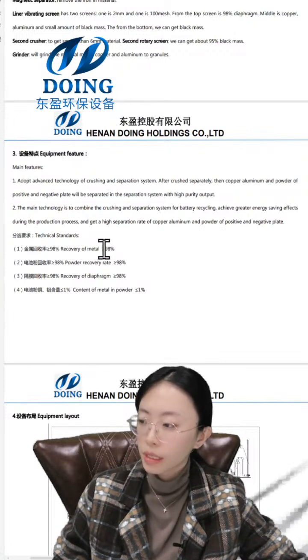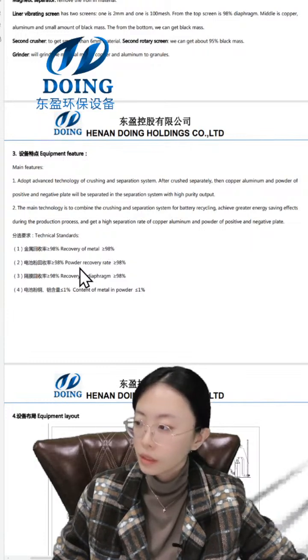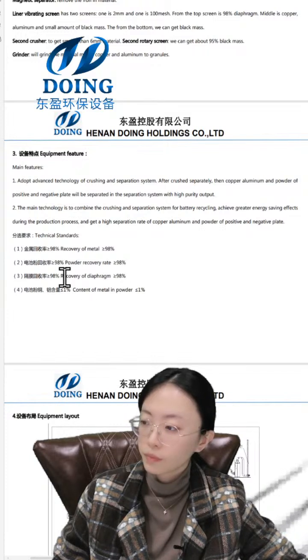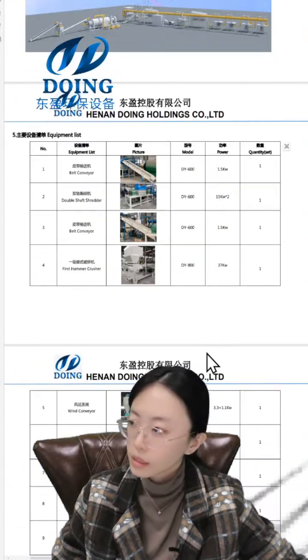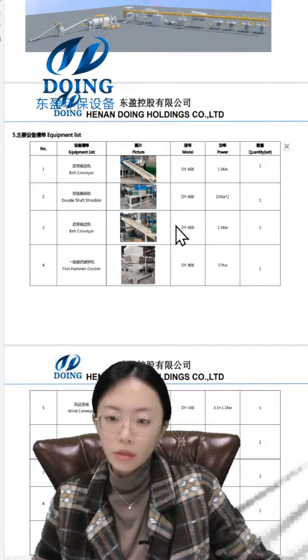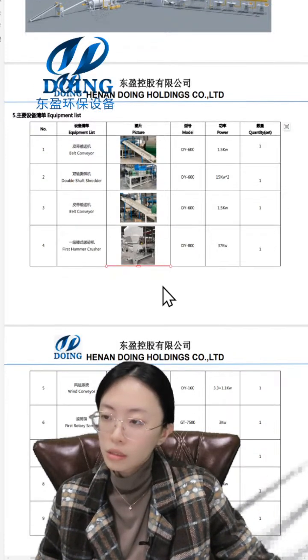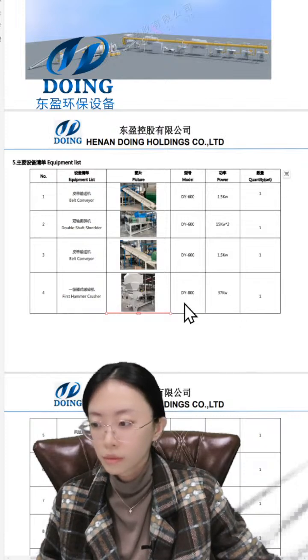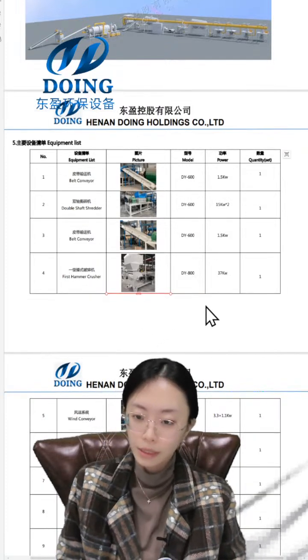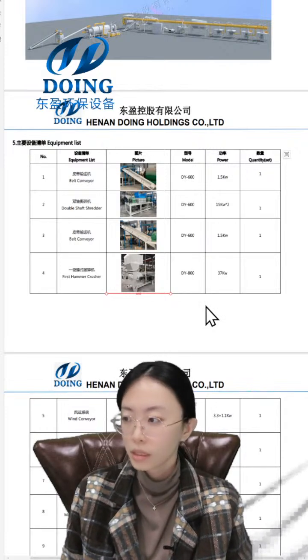Here is the recovery of the metals, 98%, and the powder recovery rate, 98%, diaphragm, 98%, and the content of the metals in the powder we can control smaller than 1%. This is an equipment list for 500 kilograms each hour for you to reference. The configuration depends on your requirements. If you need high efficiency, you can add more separation devices. You can see what equipment we have, besides the devices that we introduced. We also have some belt conveyors and wind conveyors linked with the different devices.